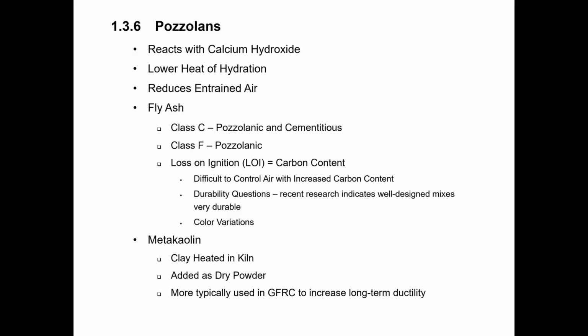All right, so one of the drawbacks to using a fly ash as a pozzolan is that we do get less early strength, and so we may not be able to turn our forms over quite as quickly as we would if we were not using the pozzolan. Another negative effect of using a pozzolan is that it is such a fine material that it can interfere with the production of entrained air. And so we may have to use more air entraining admixture in order to get the desired level of air entrainment than we would if the pozzolan was not used.